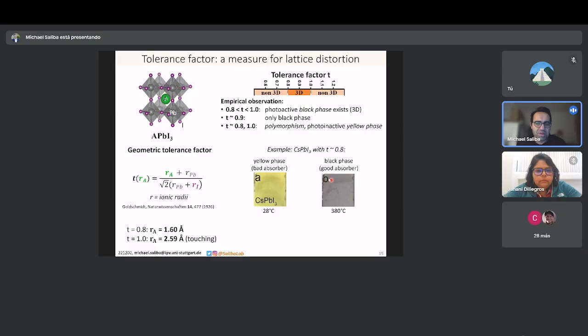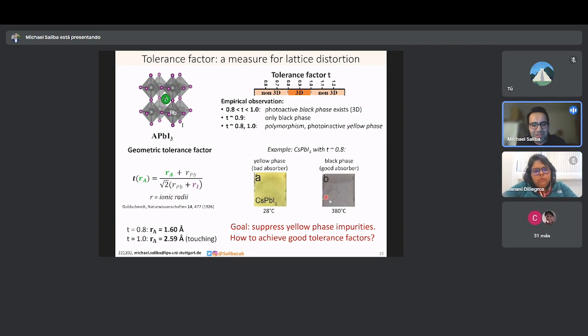So that's what we call it in literature. And this example of cesium lead triiodide exemplifies that the yellow phase, which is a very bad absorber, is what you get at room temperature, and only when you go up in temperature you get the black phase. So how to avoid that? How do we suppress this yellow phase? How do we stabilize the perovskites in their black phase at room temperature? That's one of the guiding questions for the next couple of slides.